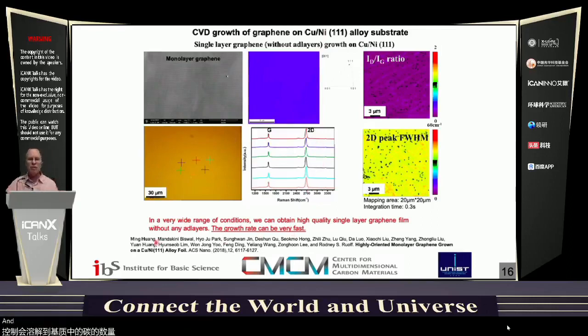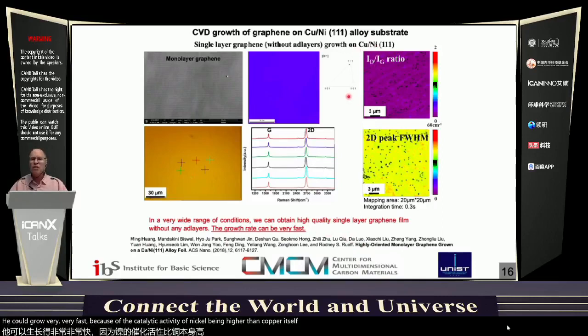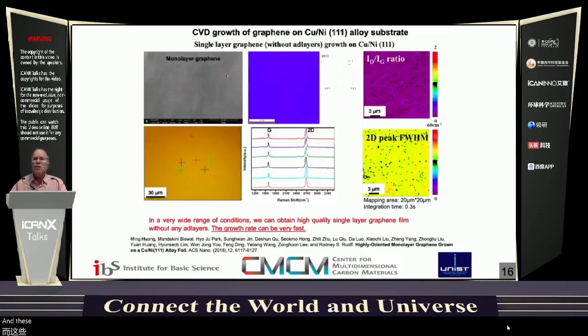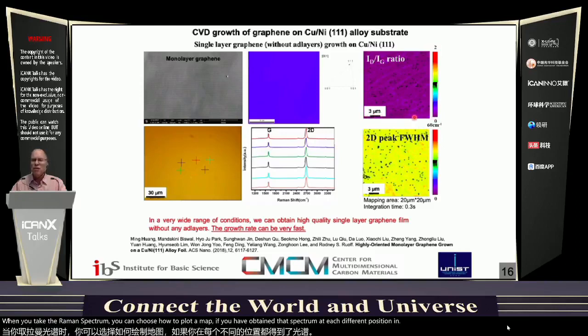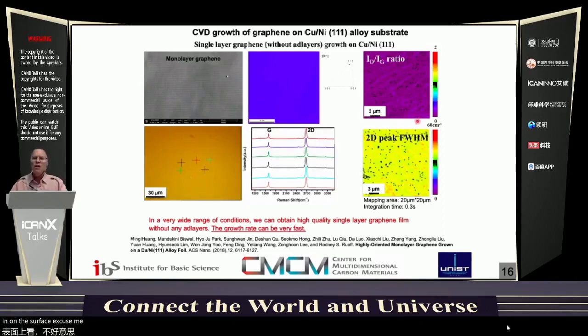And Ming was able to find out, along with help from the co-authors, that he could grow very, very fast because of the catalytic activity of nickel being higher than copper itself compared to pure copper, very high quality graphene. And these maps that you're seeing, where you have a lot of pixels here, when you take the Raman spectrum, you can choose how to plot a map if you've obtained that spectrum at each different position in space on the surface. So this very uniform color, with the exception of the black dots, means very high quality graphene, as do these sorts of Raman spectra here.